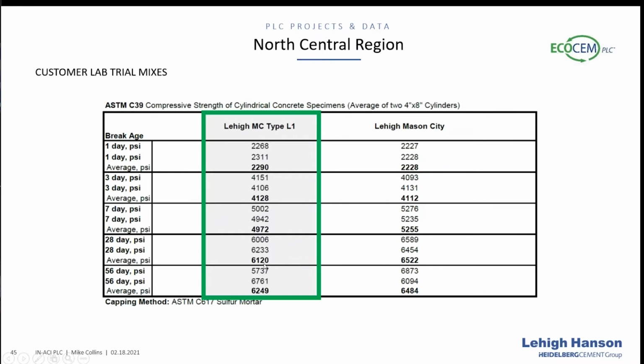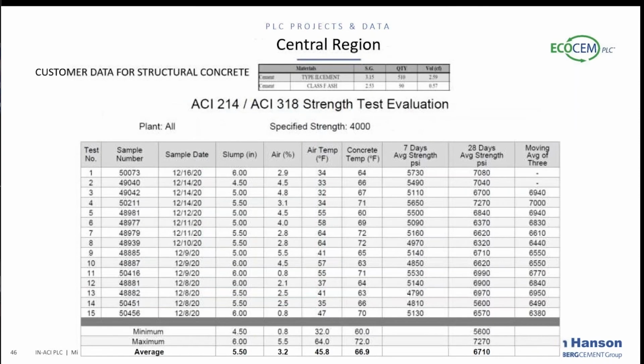In terms of strengths, the same kind of properties continue to bear out, where we're seeing very equivalent, like for like strength performance, well within standard deviation. And again, the report that we got back from our customer after they did their trial mixes was that they were very pleased that the results were so similar. So this is a good report where we didn't have our hands in this testing. This is a customer doing our testing, some evaluation for their own purposes.